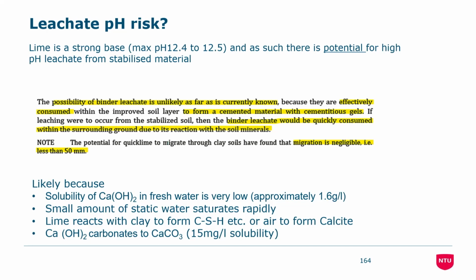And it's likely in certain ways because of some of the chemistry behind this. So the solubility of calcium hydroxide, which is what the cement and the lime will have within it, is very low. If we were to think about that in terms of an amount, we would get about 1.6 grams per litre. That's not very many grains of salt, grains of sugar, if you think of it in that way. So that's its maximum solubility before you can't actually get any more out. So therefore, if you've got a small amount of static water, that's going to saturate relatively rapidly, so it's not going to lead to a large scale, ongoing leaching problem.